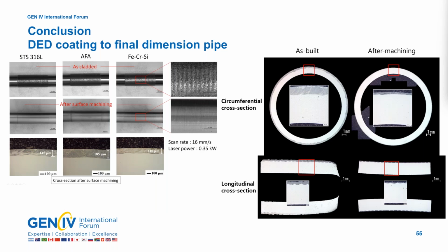To match the target surface roughness and coating thickness, subsequent surface machining on the as-cladded surface can be performed. In this case, as shown in the right-hand image, an improved surface finish and thinner coated layer can be achieved.